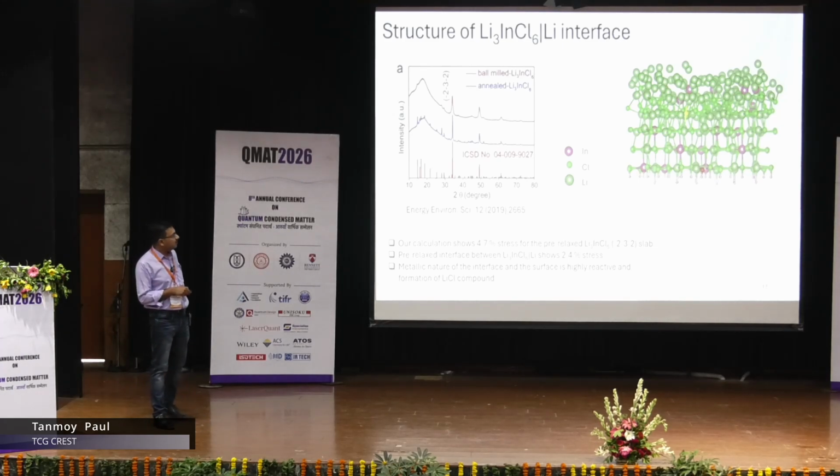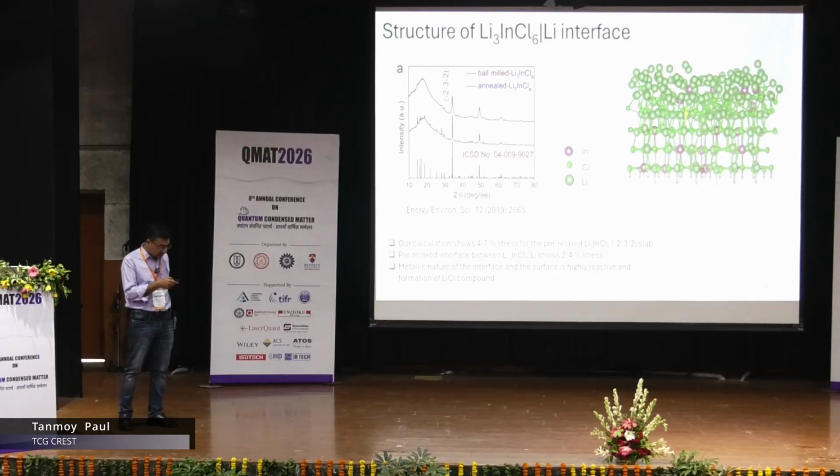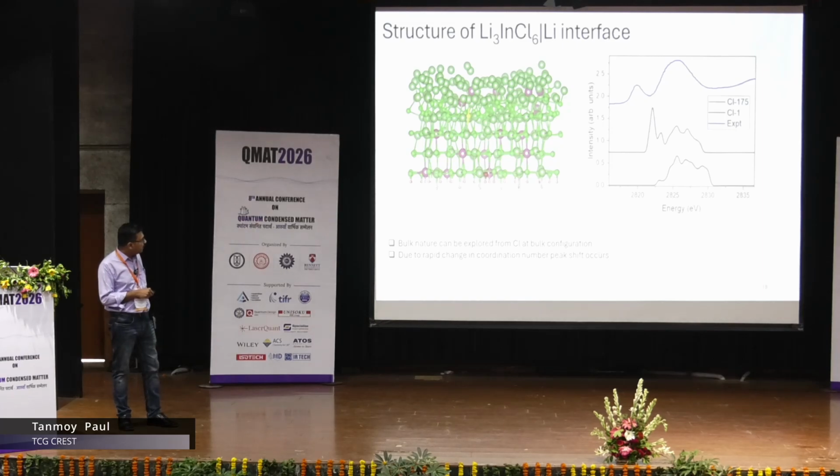This is the interface after structural relaxation, and we already find that lithium and chlorine make a bond, and lithium chloride is formed. We find that this is a reactive interface and there is a bulk-like nature. We studied the excitations from the chlorine from both sides, and we could see that this red one comes from the bulk-like nature, and this one corresponds to this spectrum.